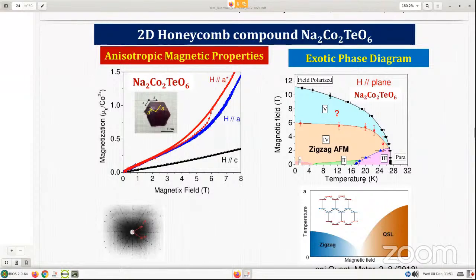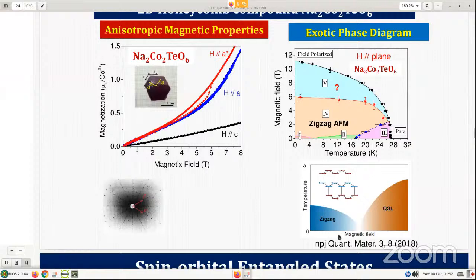Magnetic field as a function of temperature we have drawn, and this is the zigzag antiferromagnetic state which you just talked about. But under field, it is going to a state which, if we compare with the theoretical work in the literature, temperature as a function of field, this is the zigzag state, but a quantum spin liquid state is expected at higher field. So whether it is a quantum spin liquid state or not, that is what we are investigating at this moment.